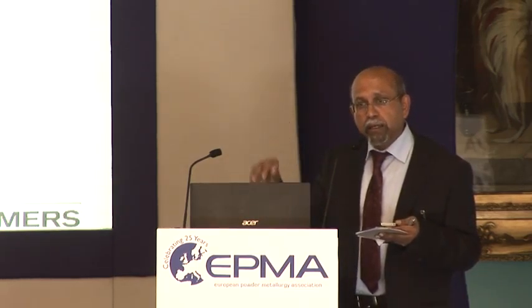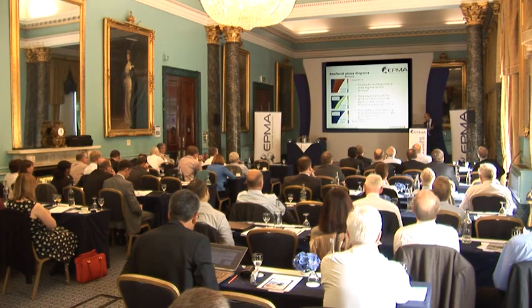What we have also been able to confirm is that grain growth inhibition in fine grain material is because, for example, when you dope with vanadium carbide, you have a very thin layer of vanadium carbide at the tungsten carbide cobalt boundary. Some of us thought we could see that, but there was no proof. Now, due to better technology in the characterization, we have proof that there's a thin layer, and we also know about the mechanisms of growth. And this is, for example, a phase diagram for an interface which shows at which concentration of tungsten, vanadium, the vanadium phase which stops the growth of the carbide crystals is active. So we can do that for vanadium, titanium, whatever.